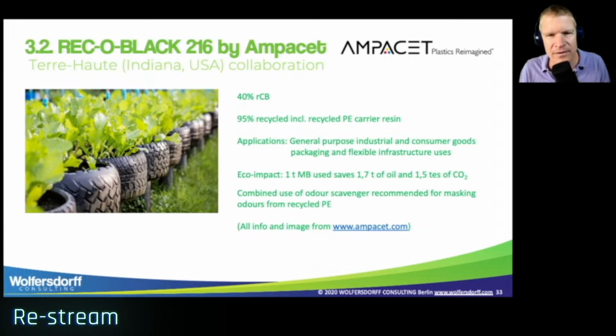It's a 40% recovered carbon black master batch. This time we have 95% recycled content. There might be some additives or some virgin polymer added to the mix. Applications are stated as general purpose industrial and consumer goods, packaging and flexible infrastructure applications. Eco impact: oil saving, of course, and carbon burden saving. Interestingly, Ampacet mentioned the combined use of odor scavenger.